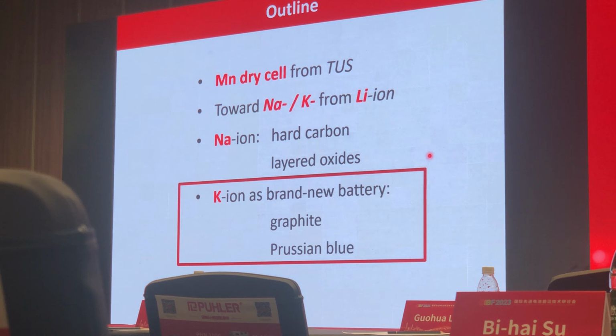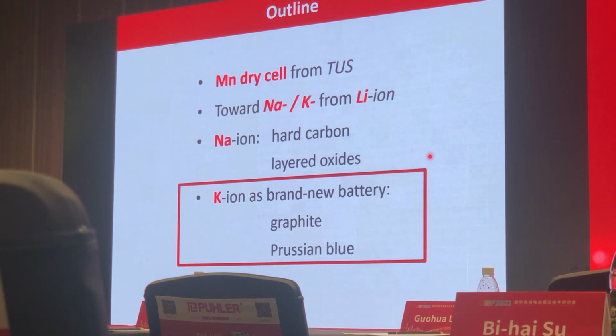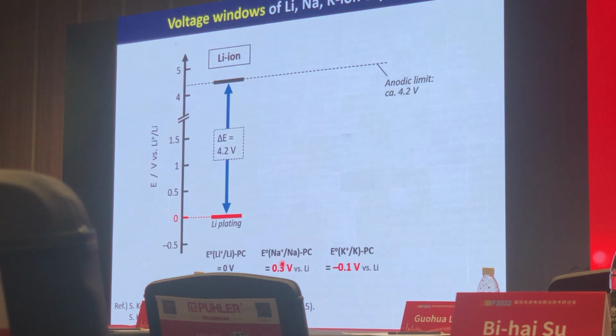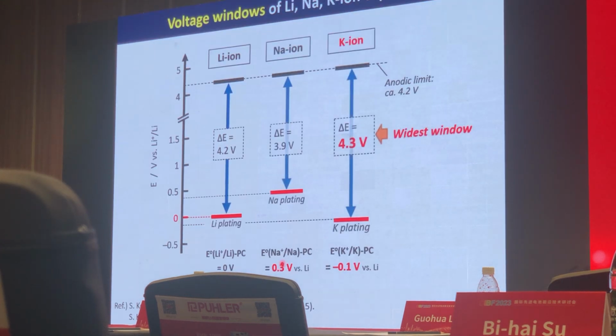So next, I will introduce our potassium ion battery, which is a brand new battery based on graphite and potassium Prussian blue, negative and positive electrodes respectively. So what is the meaning of potassium ion, which has a heavier atomic weight than lithium and sodium? In the case of lithium and sodium, the potential window is narrower for sodium ion because sodium operating potential is higher than lithium. But it is surprising that in the case of potassium, the operating potential is lower than lithium because the operating